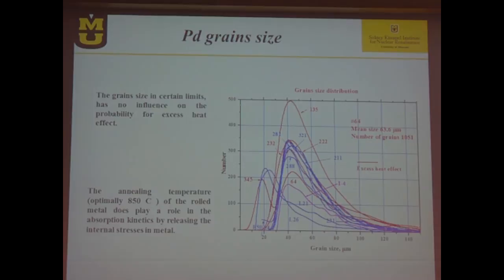Then we thought that maybe the grain size has to do with it. So we conducted a very substantial set of experiments, changing the grain size by changing the annealing protocols of the cathode. You can see that the blue curves are those which didn't produce excess heat. The red, those which produce excess heat. But they have exactly the same grain size. This is the grain size distribution. So that also did not give us an answer.